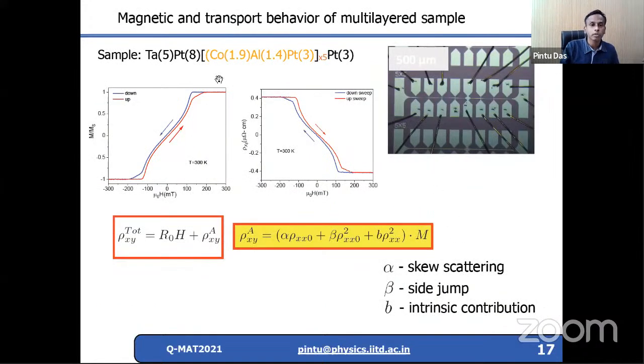In collaboration with the CNRS Thales Research Group, Vincent Cros, we are working on this system. This is a cobalt aluminum platinum system. This film is prepared by them, and we are performing all the measurements here. We made a few devices out of that film, and this is the magnetization measurement and Hall effect measurement. Now in the Hall effect, typically you will have an ordinary Hall effect plus an anomalous Hall effect. Anomalous Hall effect consists of these components: scattering, side jump, as well as an intrinsic contribution, which is also dependent on the magnetization behavior of the system.